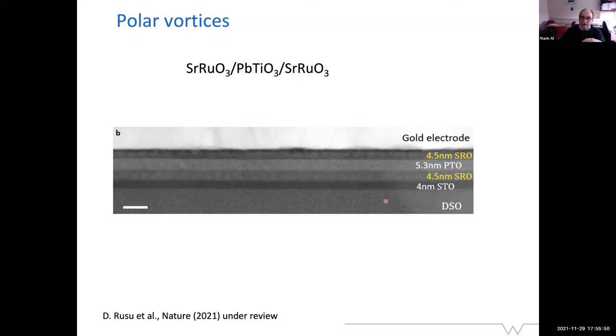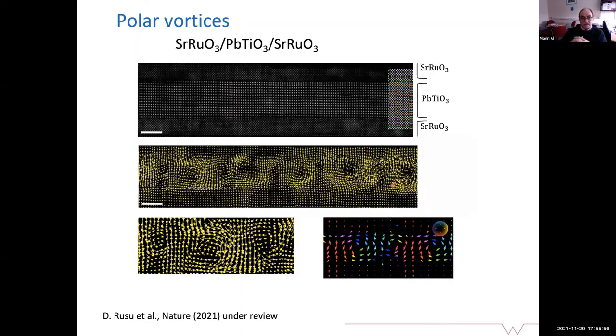We did this over an entire range of thicknesses, but I will present only one now because that's the most interesting. And doing, again, scanning transmission electron microscopy, we observed the same, or a similar, behavior in terms of the occurrence of polar vortices. Again, we have polar vortices which are periodic, and they also have different, opposite chirality: -1, +1, -1, +1 chirality. And this is the DFT calculation.